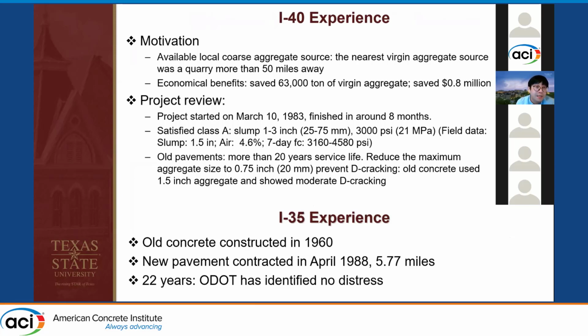So for the I-40 JPCP section, the motivation back in the 1980s was that the contractors really could not find a very nearby quarry which can supply virgin aggregates. So therefore, they decided to use recycled concrete aggregates from the old pavements, and it ended up they saved about 63,000 tons of virgin aggregate, and about $0.8 million back at that time. And the project started on March 10, 1983, and it was finished in around 8 months.